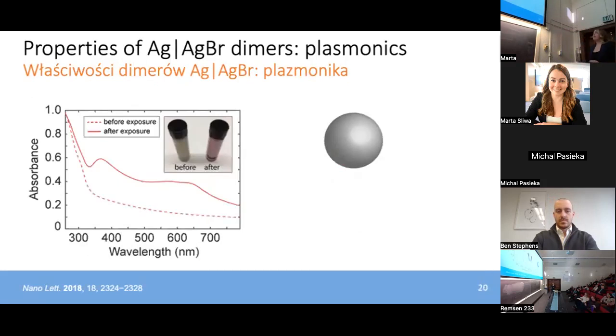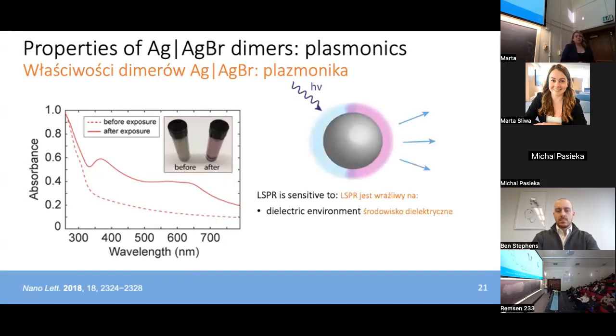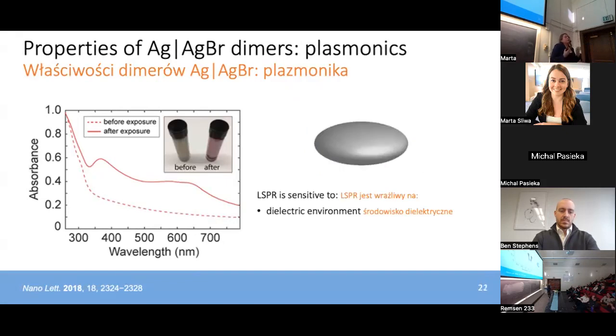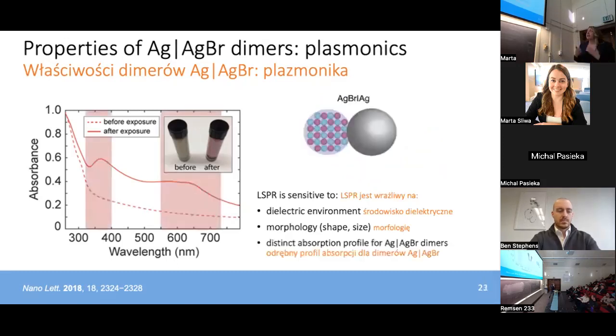So we know that a single isotropic metallic nanoparticle like silver, when I say isotropic, I mean symmetric all the way around, when it's irradiated with light, will have an absorbance profile with a frequency and therefore wavelength corresponding to its plasmon resonance. Now, when the dielectric environment of that isotropic nanoparticle is altered, perhaps by introducing some sort of differential ligand coverage or bringing a secondary material close to one of its facets, the frequency or wavelength of that plasmon will be altered, which is denoted here by that different color of arrows that represents that plasmon frequency. If you change the shape of the particle altogether and have, say, something more oblate or oval-like, the frequency of that wave or wavelength of that particle's plasmon is changed even further. So I just gave you a very quick crash course into plasmonics, and we know how the dielectric environment and the morphology or shape of the silver particle can influence its optical profile.